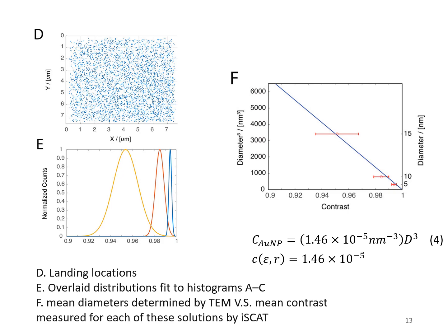The method used in the experiment involved observing the interferometric contrast of the particles and creating a regression line between the interferometric contrast and the known size of the particles.